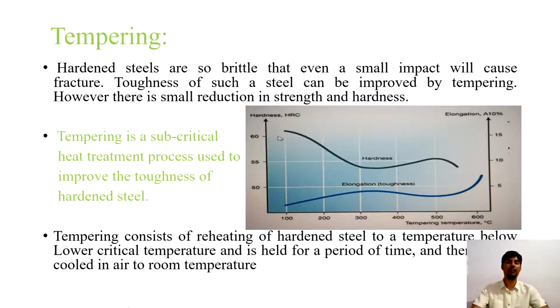So the tempering process is always followed after hardening, because after hardening we got a brittle structure which is very hard in nature. So a small impact can cause it to fracture. So in order to reduce such brittleness from the material, we will follow the tempering process after hardening. Tempering is a subcritical heat treatment process used to improve the toughness of the hardened steel. Tempering consists of reheating of hardened steel to a temperature below lower critical temperature, that is below the A1 line. We will again reheat the hardened steel below its A1 line, below its lower critical temperature, and hold it there for a period of time and then slowly cool it in air to room temperature.